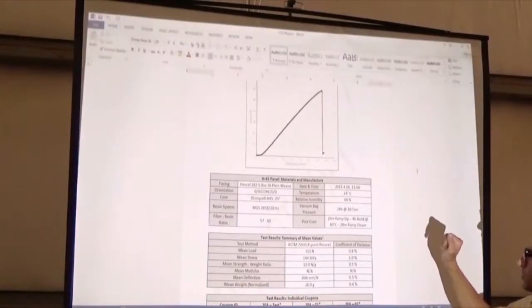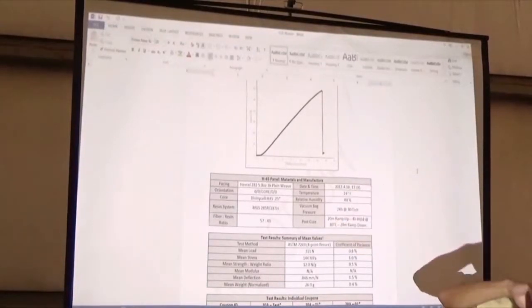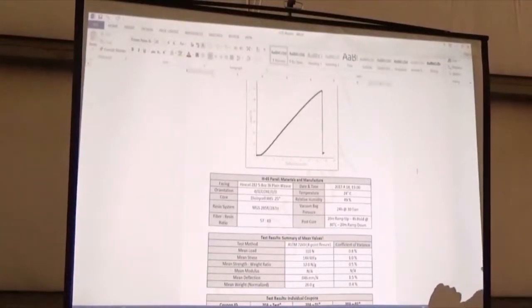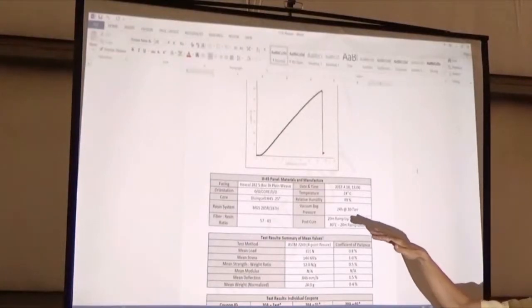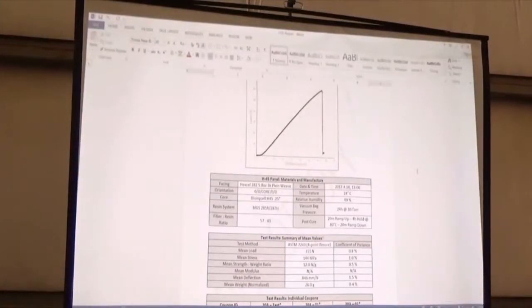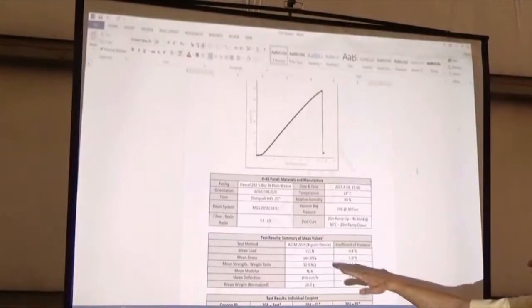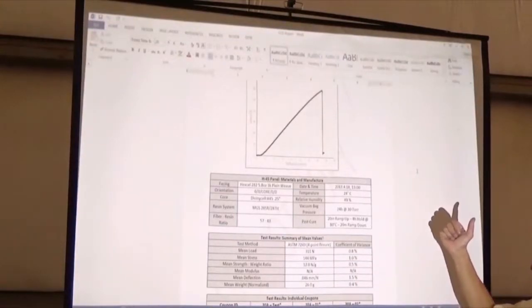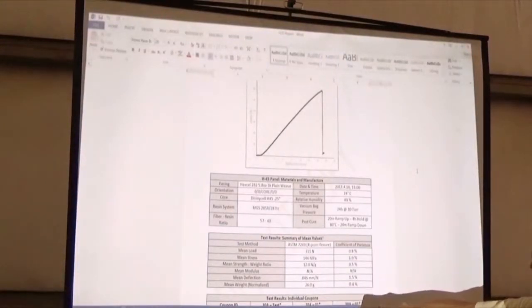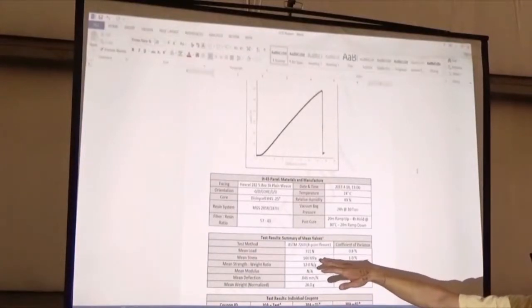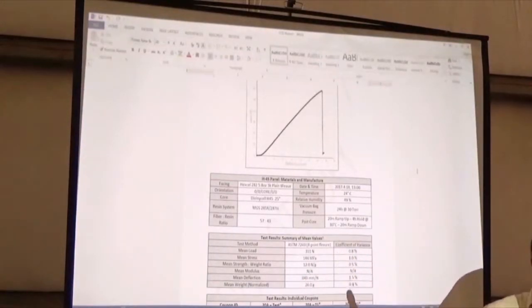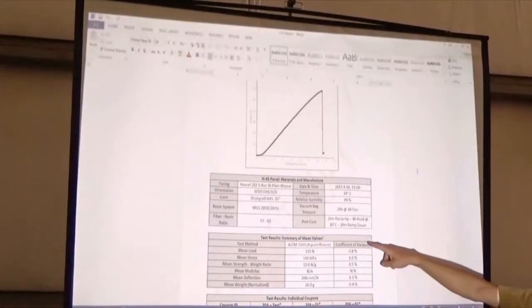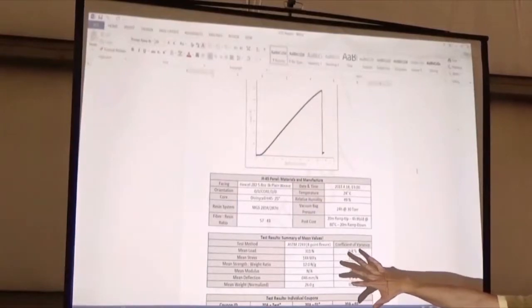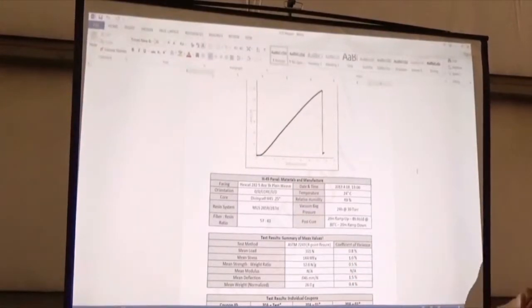And then I also do a post-cure. I'll talk a little bit more about post-curing later, but post-cure has a huge effect on materials performance. Then we're taking some data like the average load of all of the coupons, what that translates into in terms of stress, the strength in pounds per square inch, deflection, and then weight. And then coefficient of variance just indicates how similar one coupon is to another.